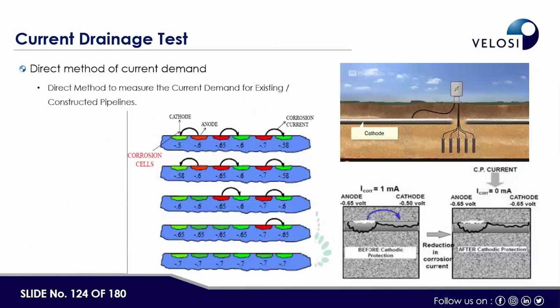Another method, what was already explained, is by desk engineering, by paper calculations. So we use the soil resistivity, we use the coating breakdown, we measure a lot of things. Another is the direct method. You have one pipeline, and before application of the cathodic protection system, you measure the natural potential. For example, we measured this potential and it varies from 0.5 volt or 500 millivolt to 700 millivolt. It may be up to 100 kilometer of pipeline, with thousands of readings recorded. We call it a native potential survey, or natural potential survey.